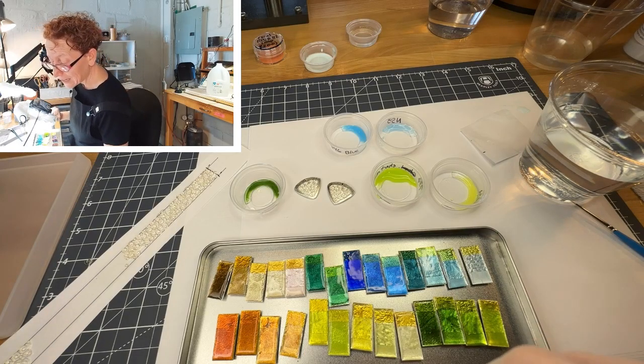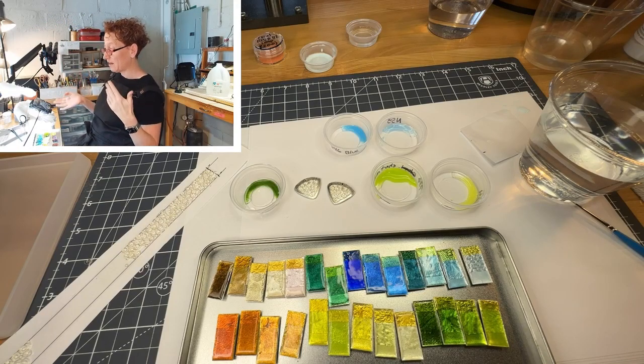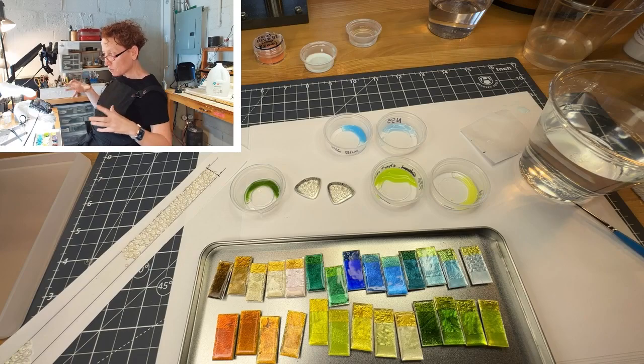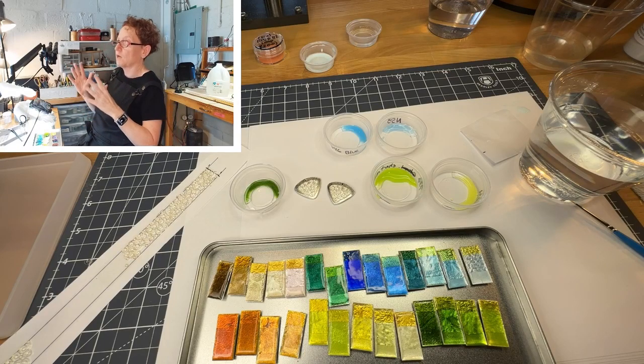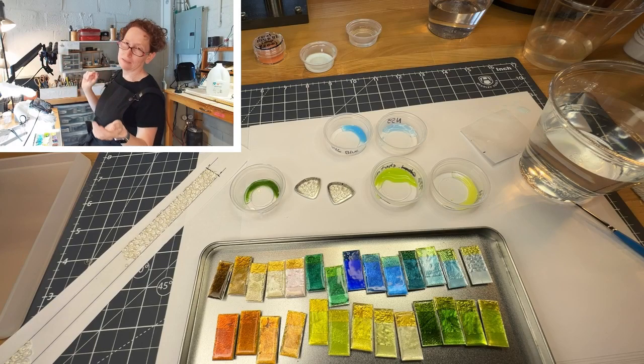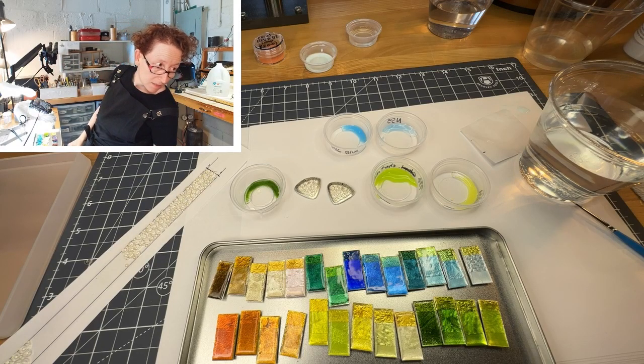And if you've got moisture in there, I don't mind a little bit of glue residue because it's opaque, but if there's moisture in the glue, what's going to happen is when it expands, because it's heating up and evaporating, you get this little eruption of the wires. The wires will kind of come up, or they'll go like this, and some of them will tumble, and it's just not great.